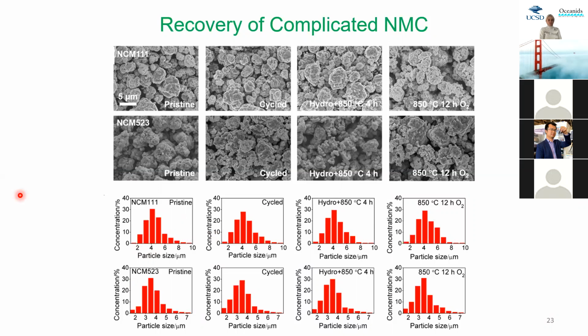Okay, this is actually further demonstrate that why we can do this so-called direct recycling, because your materials itself, maybe 80% of them are still good. We don't have to do a lot of harsh treatments to crush these particles to dissolve them into strong acid, because we spend so much time and effort to make them to form such a morphology. Okay, so which is something we should maintain, we should keep. So this is also the reason, the advantage, the rationale that we have to do direct recycling.